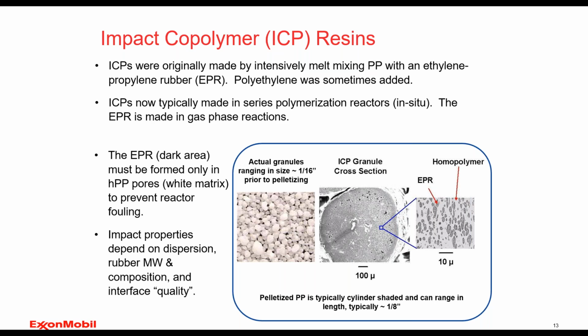The rubber domain, the EPR, is the dark spots. The homopolymer is the white area that's continuous through that phase. And the rubber domain is what allows the energy to be absorbed. And depending on the size and frequency of those domains can offer that tailored property performance for whatever degree of toughness you might be looking for, just a touch of toughness or a product that's all the way completely a no-break status in terms of IZOD and offering like 320 inch-pounds or greater of blunt force, like Gardner impact results.